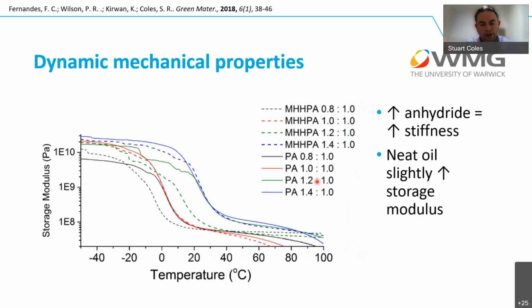We then looked at some DMTA just to understand some of the mechanical properties of this system. The plot here is storage modulus against temperature. We found here that when we had more anhydride, we were getting a stiffer material. Again, not a massive surprise, because we're increasing effectively the cross-linking density by having more of the hardener present, which you would expect to increase the stiffness of the material. The neat oil materials had a slightly higher storage modulus as well. Again, it has a slightly higher level of initial functionality that it can react with, so you would expect it to have a slightly higher cross-linking density and so on.